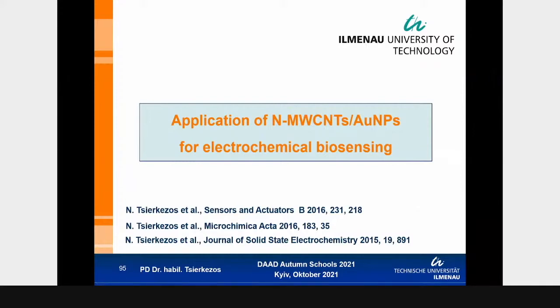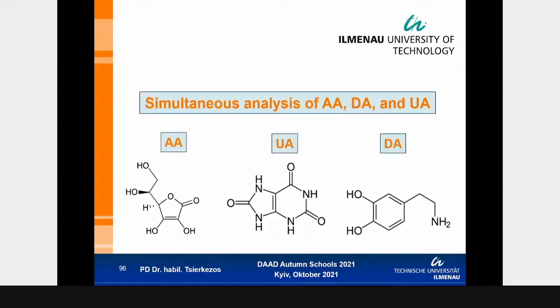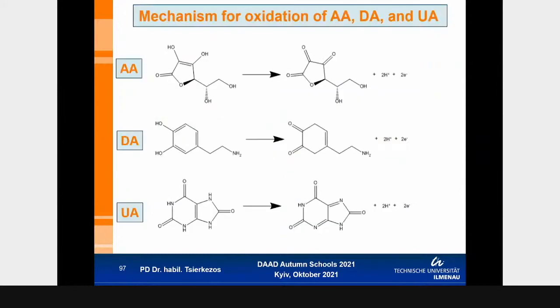After all of this characterization, we have applied the carbon nanotubes modified with metallic nanoparticles for electrochemical sensing. For this study, we have selected the nitrogen-doped carbon nanotubes, which are the best carbon nanotube material from those which are produced, and we modified them with gold nanoparticles of the size which were already investigated and worked better. So, for the electrochemical analysis, we have selected at the beginning 3 important biomolecules, the ascorbic acid, the uric acid, and dopamine, which have almost similar electrochemical processes.